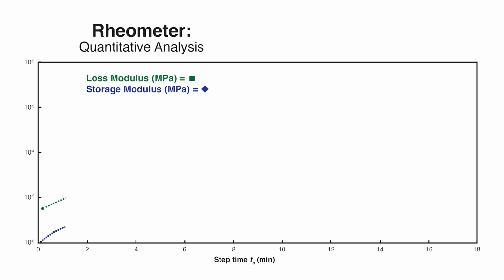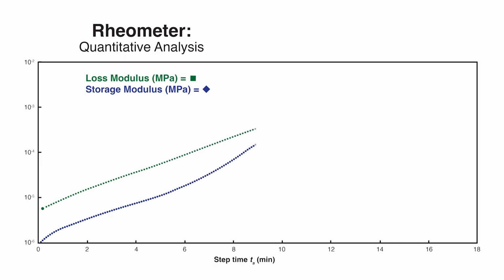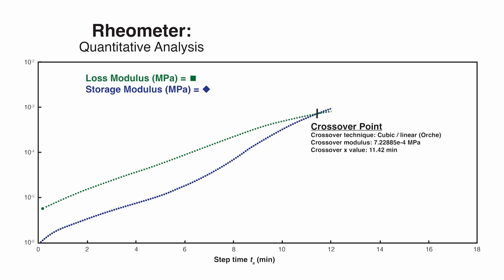In this graph, you will see the quantitative analysis of the loss and storage modulus of a curing thermoset. As the two-component thermoset begins to react, you can see that both the loss and storage modulus increase. They will both continue to increase until they reach what we call the crossover point. At this point, the elastic properties overtake the fluid properties. We relate this to the no flow point in the reaction, which is analogous to the gel time.